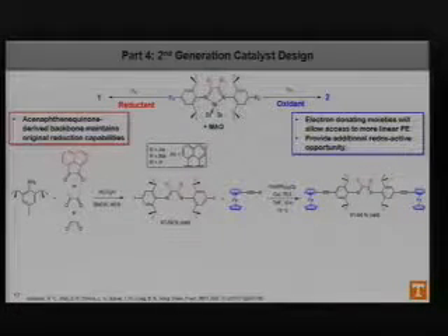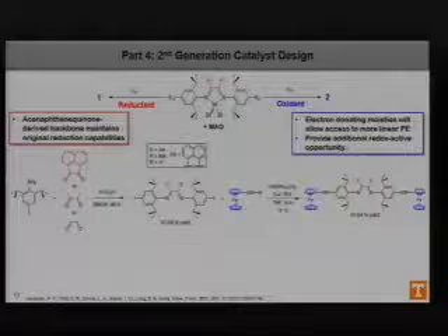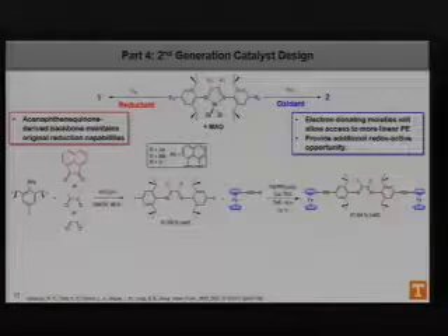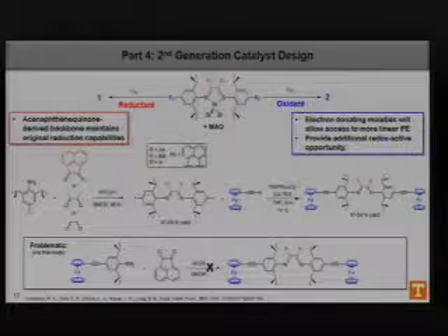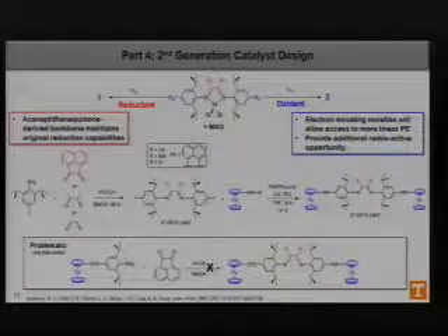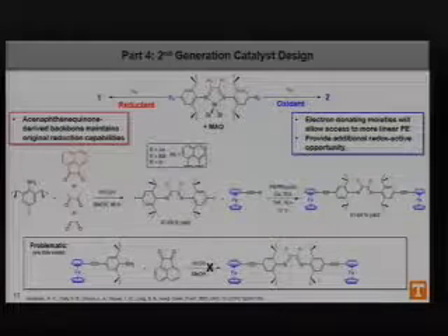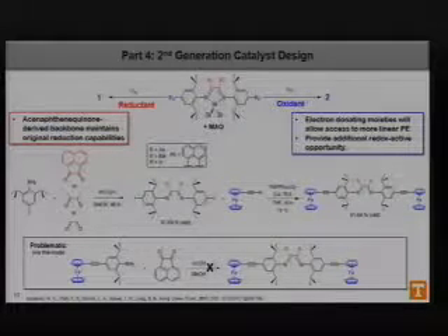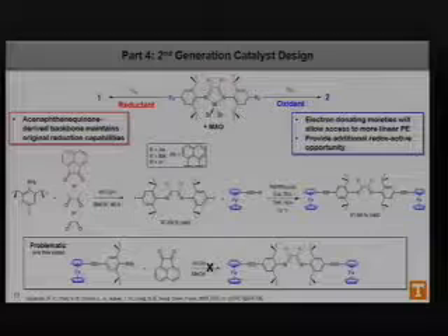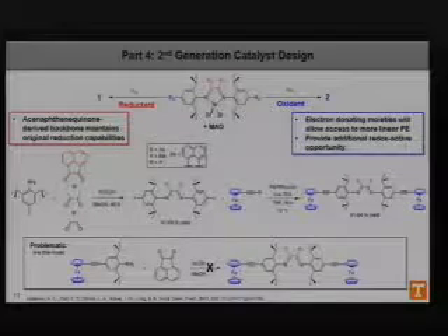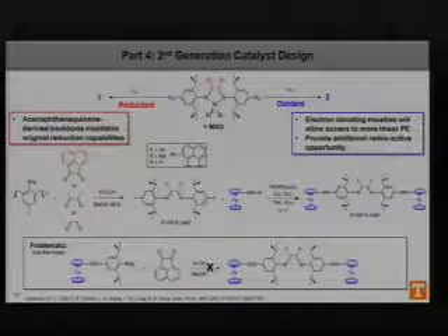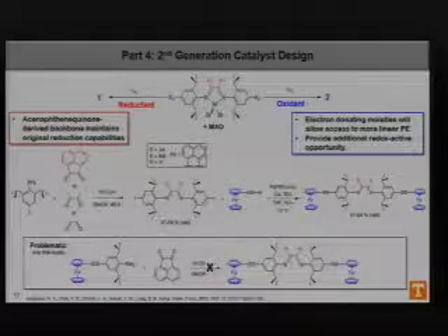Now, some of you that have done organometallic synthesis might ask why we would try and do a double Sonogashira coupling, and that's because, like most chemistry, we tried it the other way and it didn't work. If you try and condense this ethynyl ferrocene aniline onto this dione, it just doesn't work. So we tried this double Sonogashira, and sure enough, that actually works.